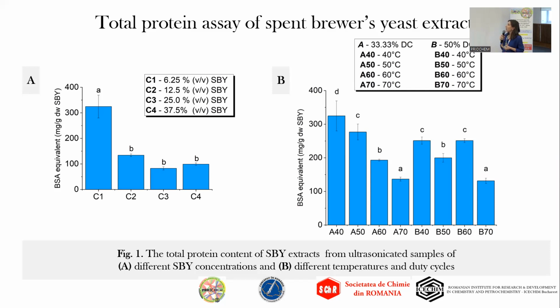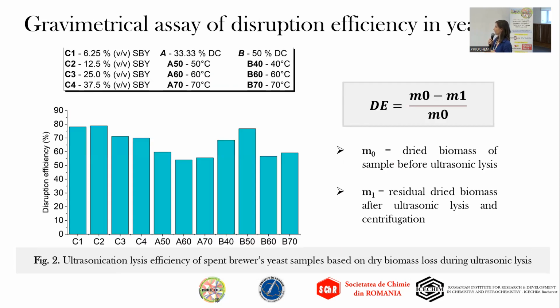The second image shows the samples with the same concentration, the optimal concentration, but the duty cycles and the temperature are varied. There is a certain descending trend with temperature. The protein content of the yeast extracts in the duty cycle of 33% decreased with the increase of temperature. However, overall, the lysis was the most efficient at 40 degrees at a 33 duty cycle. Because high temperature can denature proteins, can cause precipitation, and could interfere with the data obtained through the protein content of the yeast extract.